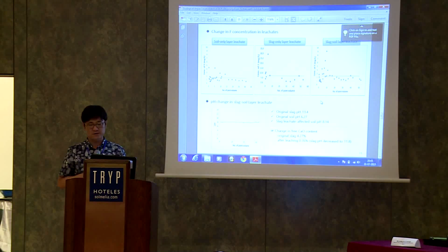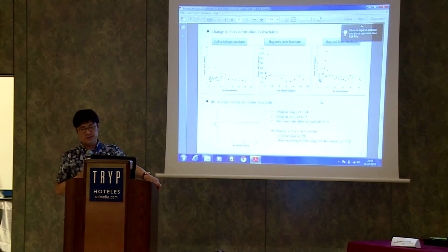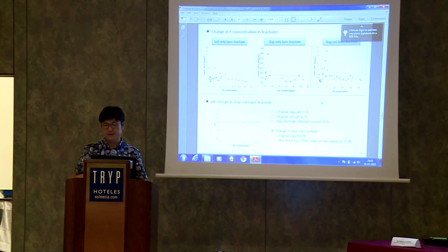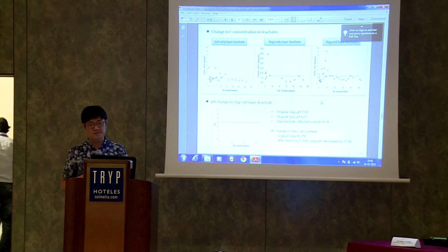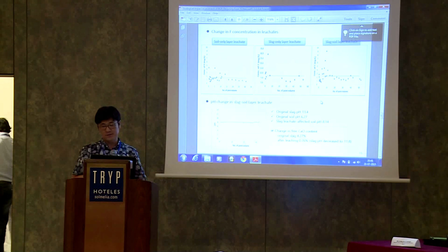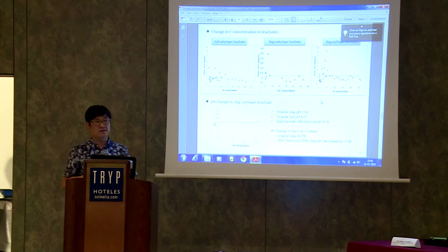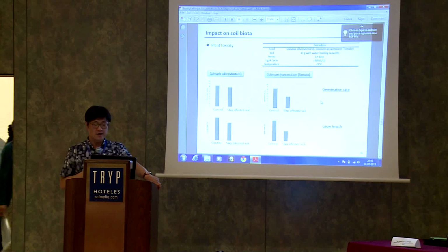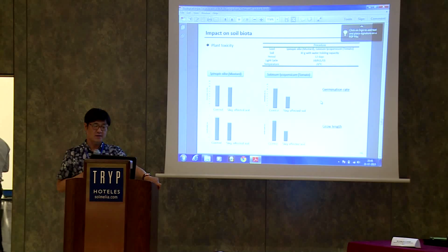Also, pH was changed. The original slag pH was about 13.4, and soil pH was about 6.27, and the slag-affected soil pH was about 8 or a little higher than that, which can be viewed in two aspects. Some can say that soil has some buffering capacity to reduce the pH, but from another standpoint, soil receives a lot of hydroxyl radicals to increase the pH. So there is some conflicting view. And also, we tested some toxicity experiments, whether the slag leachate affected the soil.